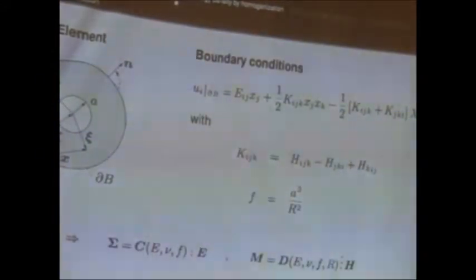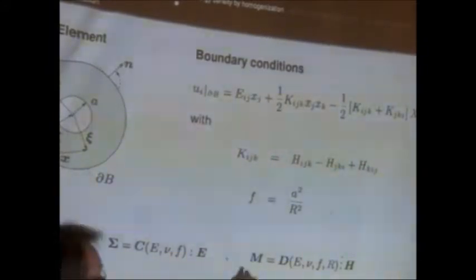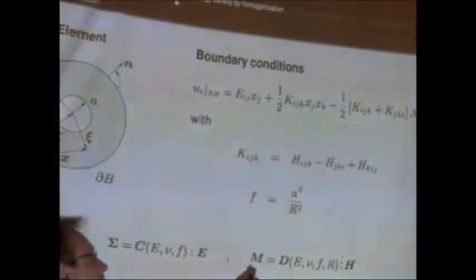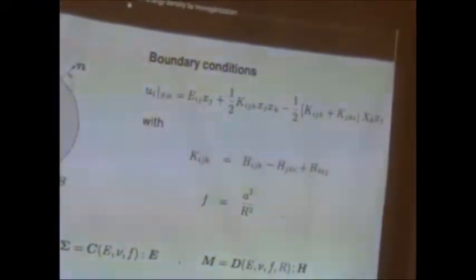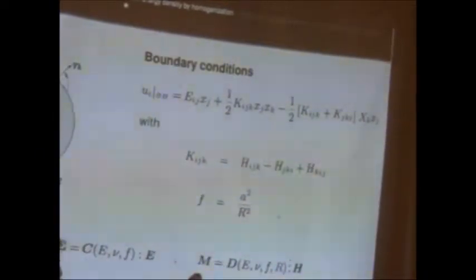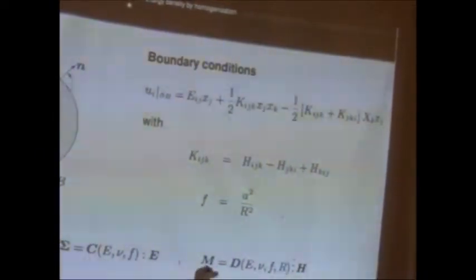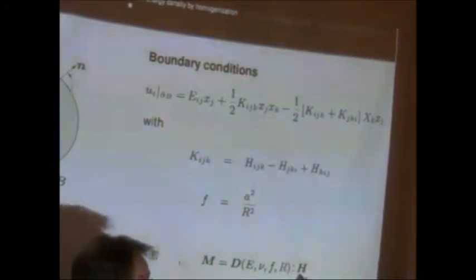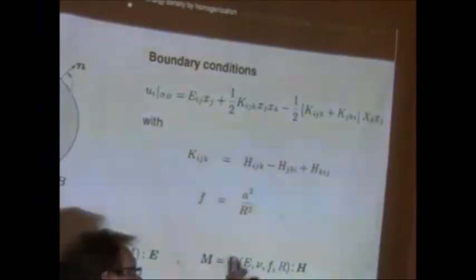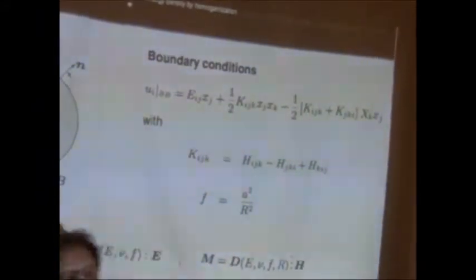Then you do the same. You solve the boundary value problem and you define, actually, this is not an arbitrary definition. You can show how you have to define your, in this case, higher order stresses. These are stresses multiplied by location. And you can relate this to the strain gradients. And this relation is expressed then by a 6th order tensor.